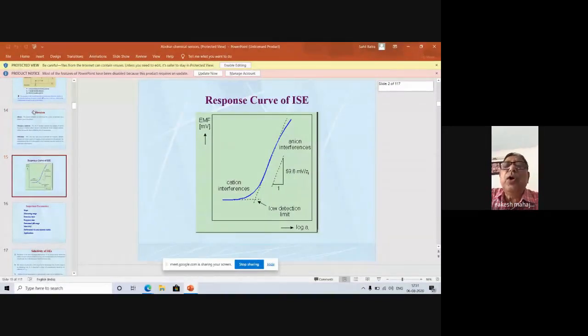This is a type of response curve, where you can see a straight line. On one side you have the EMF, that is the potential difference in millivolts, versus the log A value, that is the log of the concentration, and you will get a straight line. From that straight line, you can measure the slope. If there is a 1 electron system, the slope can be 59 millivolts. If there is a 2 electron system, the dication is there, then you can have a 59 divided by 2 slope. That is the slope measurement and the detection limit.